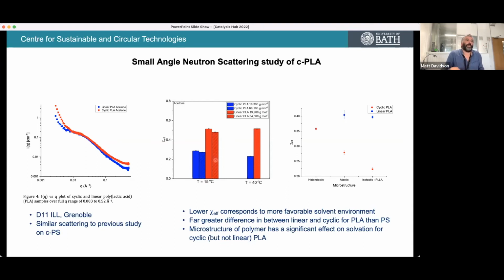And the other interesting thing that we're seeing here is because we've got samples with controlled microstructure, which hasn't been looked at before. We've got the heterotactic example that we've made with the zirconium catalyst. We've got atactic examples made with the tin catalyst, and we've got isotactic examples that can be made with either, in fact, but just using the pure monomer rather than the racemic monomer. And if we just focus on the cyclic PLA, we see the polymer microstructure has a significant effect on solvation for the cyclic, but in fact not the linear PLA.